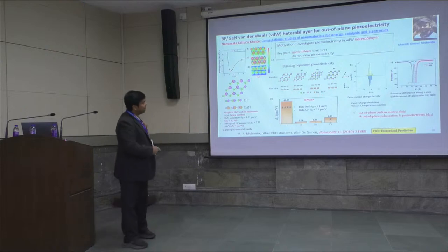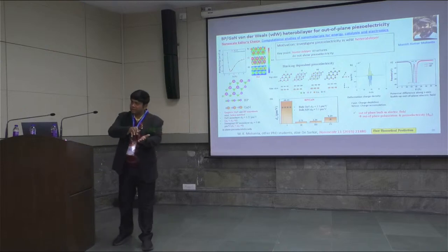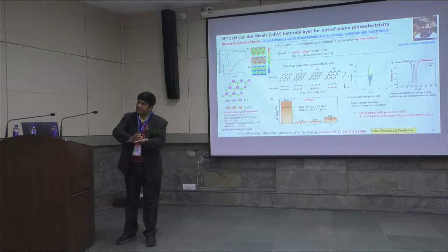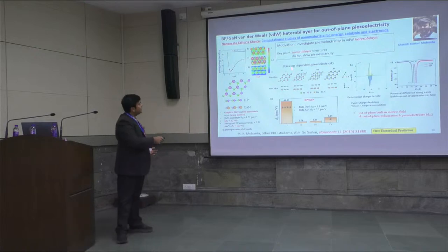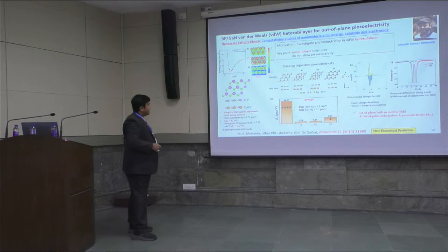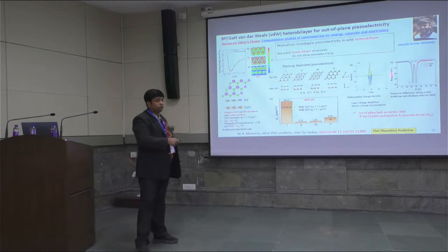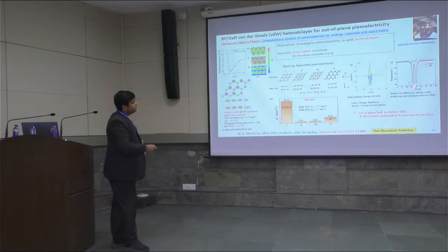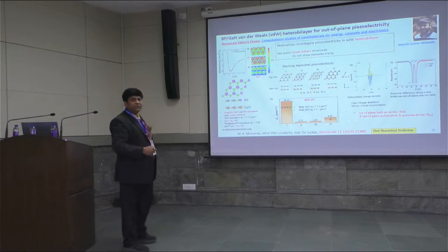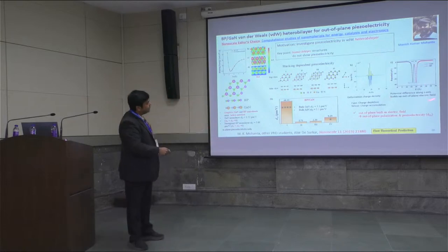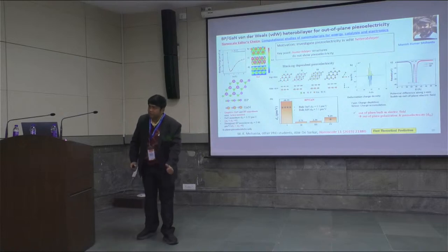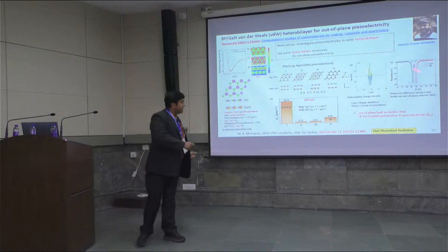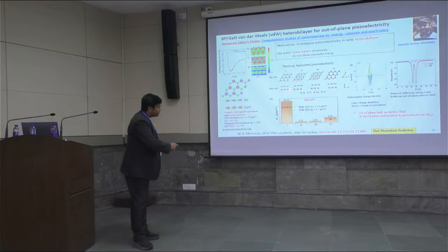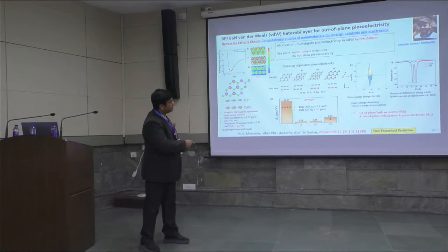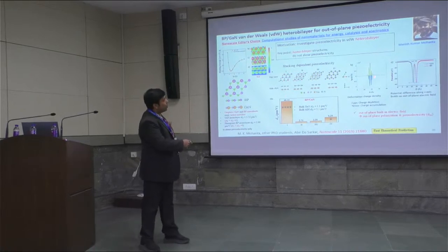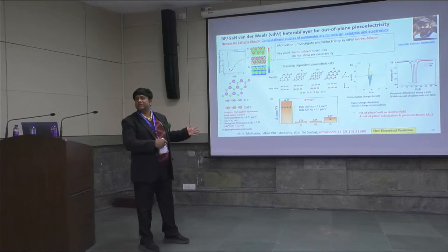In the stacking order where the layers are in perfect registry with one another, the interface dipoles are perfectly oriented along the z direction, and the highest level of out-of-plane piezoelectricity arises. And then we ascertained the origin of this out-of-plane piezoelectricity. It owes its origin to the difference in the electrostatic potential between the individual monolayers. The negative gradient of this potential builds up an electric field along the z direction, an out-of-plane electric field, which polarizes the electronic cloud on the van der Waals hetero bilayer, which is evident from these oscillations in the deformation charge density, alternating spatial regions of charge accumulation and charge depletion.